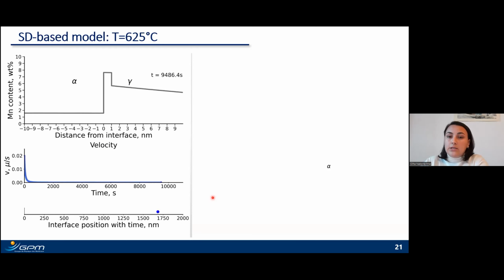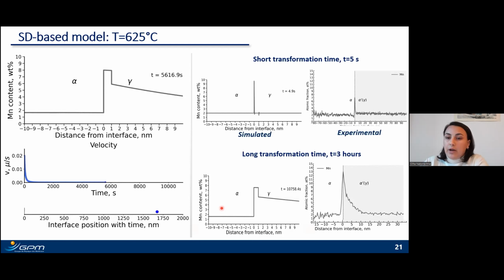625 degrees Celsius. In this video, you can see directly the evolution of the manganese profile with time and the evolution of the average velocity of the interface that was determined from the dilatometer data. You can also see the position of the interface with time. If we compare the predicted profile for different transformation times, short and long, we can see that the profile predicted by solute drag describes the experimental observations much better.